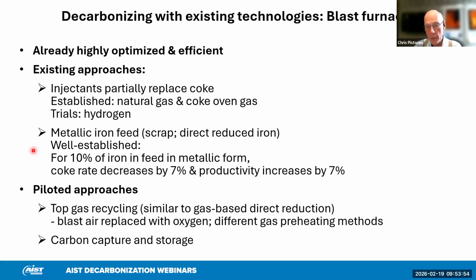This requires substantial changes. You cannot run on air, you need to run on oxygen or highly oxygen-enriched input gas. And typically there is some requirement to preheat this gas, of course, as it goes into the furnace, and that's then different than the existing stove approach. And then, as Sarah mentioned, carbon capture has been piloted, hasn't been implemented at a large scale, but still has some scope from a cost point of view. It seems attractive, although in the absence of a large-scale demonstration, one doesn't really know what the true cost will be.